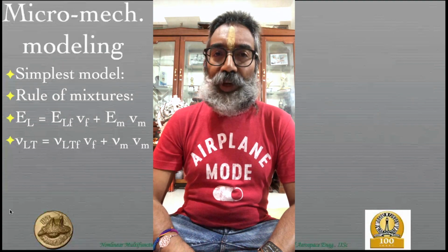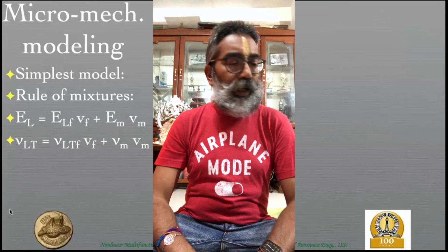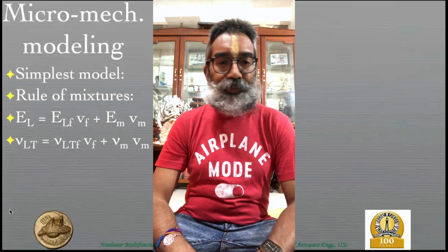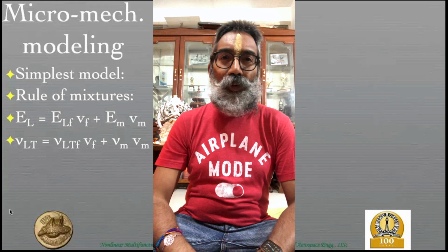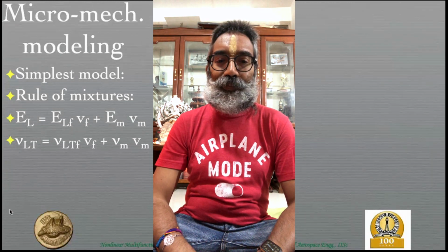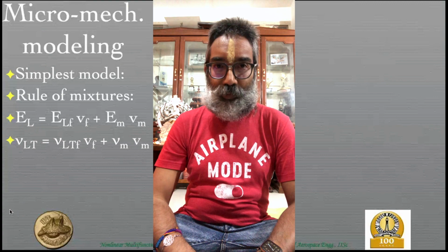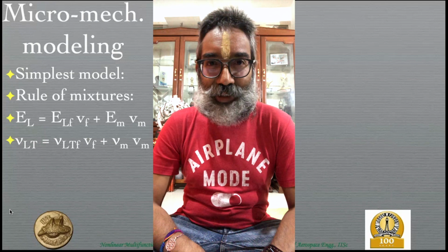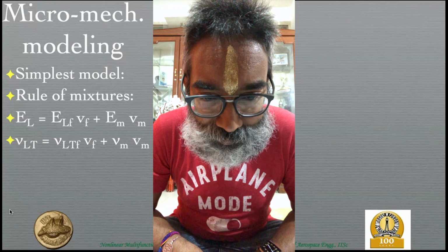Now for isotropic materials, you know that the Poisson's ratio has a particular range. Can anybody tell me what is the minimum and maximum values of the Poisson's ratio? It's 0 to 0.5. Okay, good. Anybody else? -1 to 0.5. Okay. So the first answer is a subset of the second answer, but the second answer is more appropriate. Yes, sir. The second answer is correct.